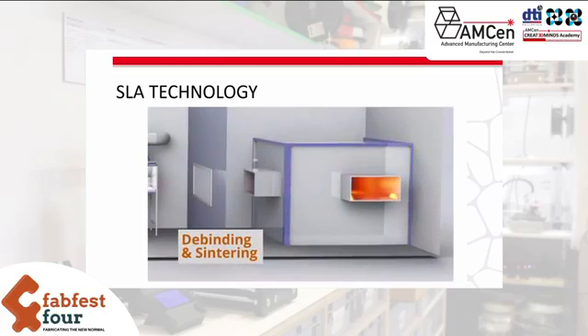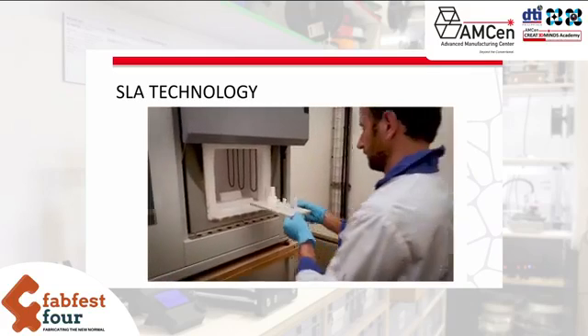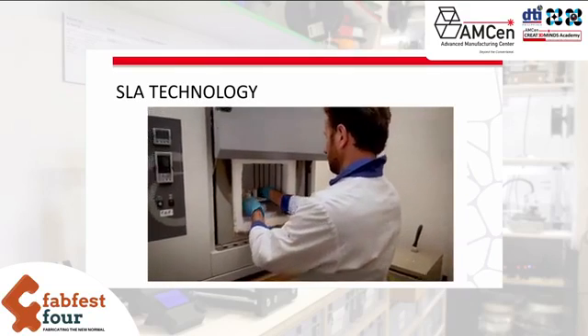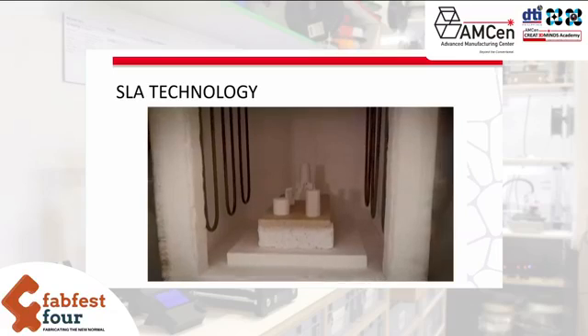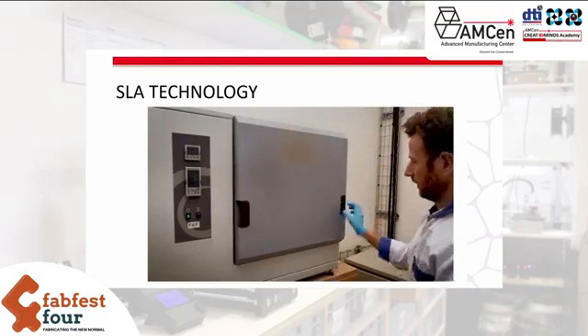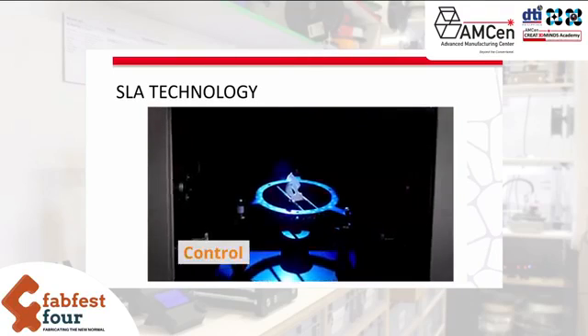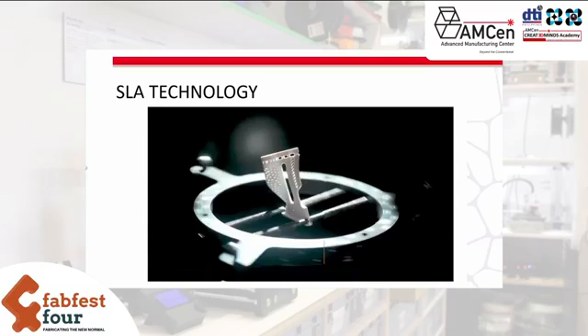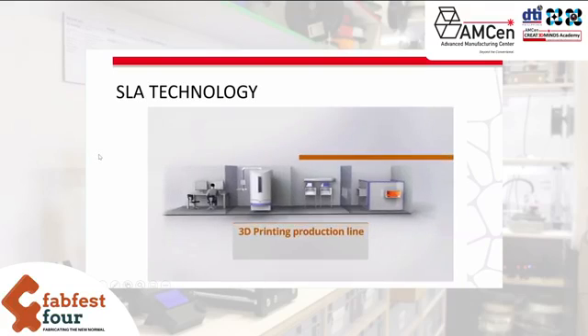And after printing, first thermal treatment, debinding, in order to burn, to remove the binder, and then sintering in order to close the porosity and to densify the part. And then after, of course, control of the size of the part if you need, if you want.